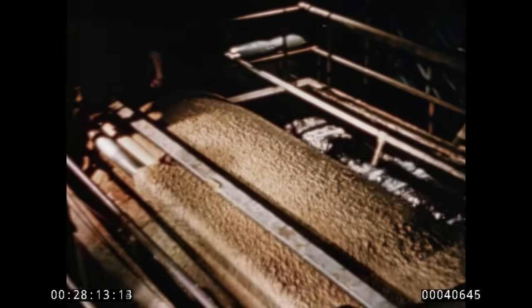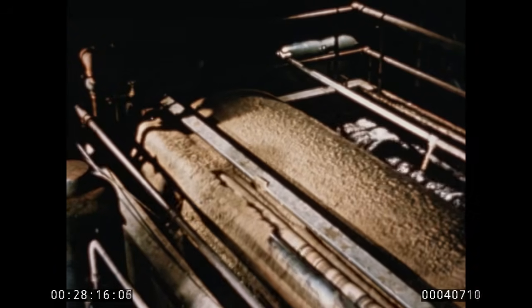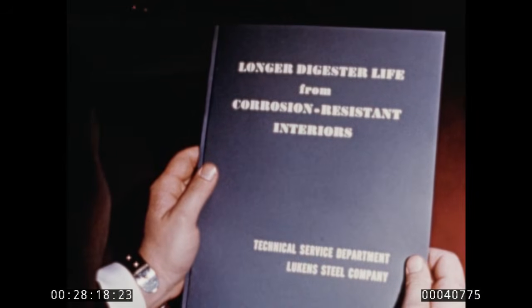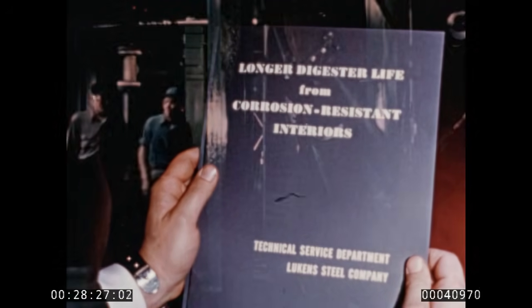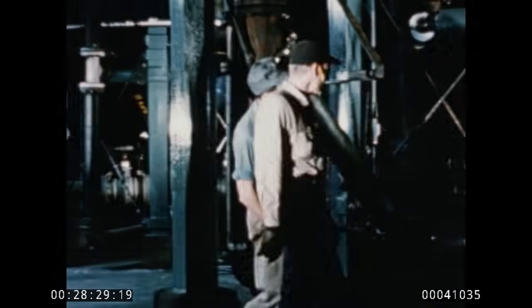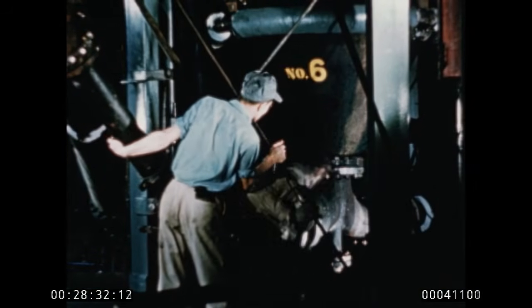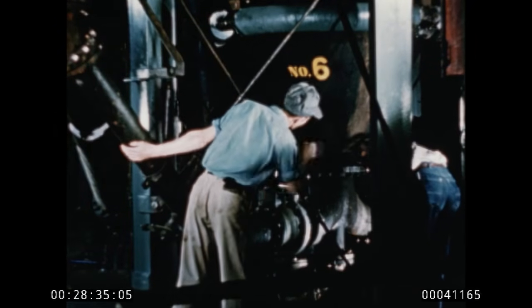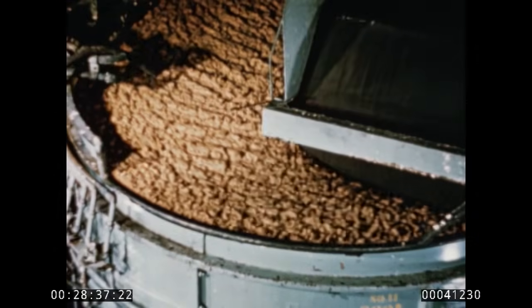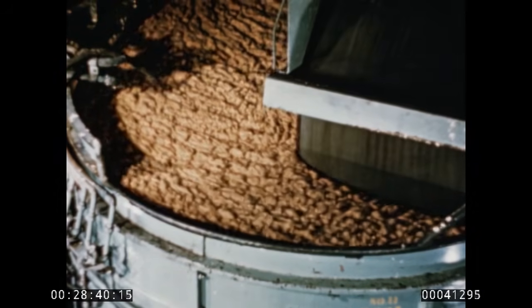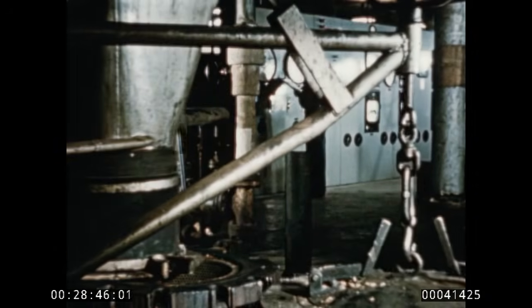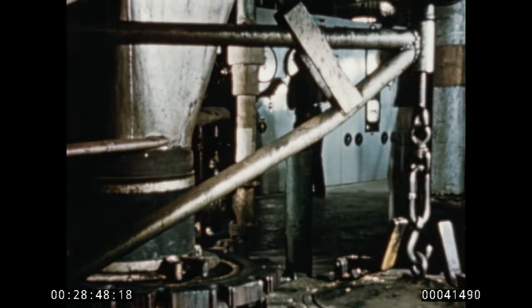Corrosion, causing short equipment life, was the problem facing this big Northwestern pulp and paper outfit. As a matter of fact, the frequency of digester failures in the pulp and paper industry prompted Lukens to make a thorough study of the problem. And that's why we decided to have these vertical sulfate digesters fabricated of clad steel. Sure glad we did. The highly corrosive cook, working at 300 degrees Fahrenheit, doesn't seem to faze the clad at all. And neither does the shock of a cold charge hitting the digesters while they're still hot.